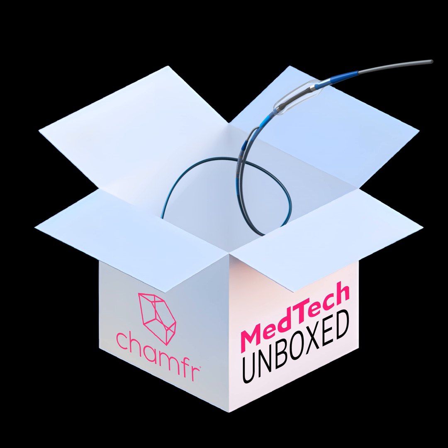That's both coming off under pressure and then creating steam immediately, so it's a bit of a safety hazard. A lot of places don't like to do that, including us, for that reason. Another option is oil, which can achieve those temperatures at lower pressures. We do exclusively medical molding in a Class 8 clean room, so oil is a dirtier material with a bigger risk of contamination. So we avoid the oil and opt for electric heating, which has some drawbacks, but we've managed to come up with a really good classic design approach that we've very much standardized to work around those drawbacks.